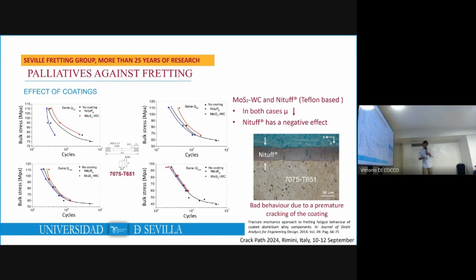The first palliative studied against fretting was coatings. In this case, molybdenum-based and Teflon-based coatings. In this picture, we can see a summary of the tests done with this type of coatings. Here, we can see the fretting fatigue lives obtained as a function of the bulk stress applied to the test specimen, and also as a function of the tangential load applied.